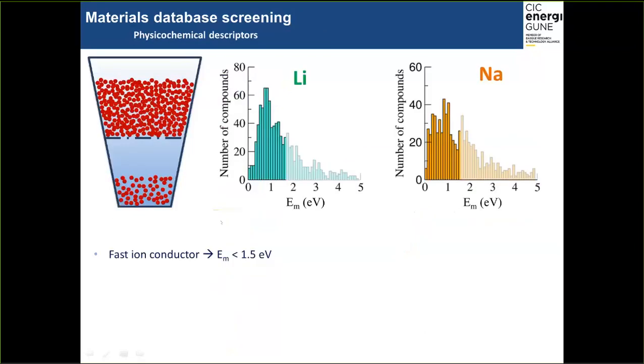But before getting into that, it is well known that the bond valence method systematically overestimates diffusion barriers, which is not surprising given the simplicity of the model. And the scaling factors in the literature for a variety of compounds and structures suggest that percolation energies of 1.5 is a good threshold to define fast ion conductors. In these histograms shown here, the compounds here for lithium and here for sodium will be the compounds that pass the filter, because they correspond to migration energy lower than 1.5 electron volts.